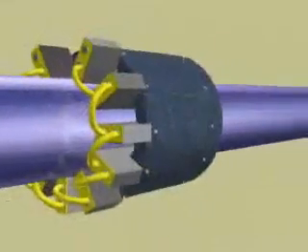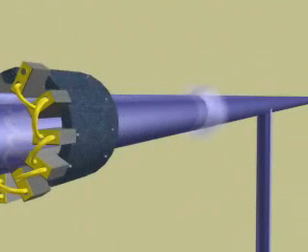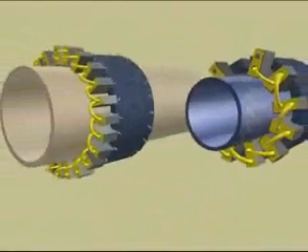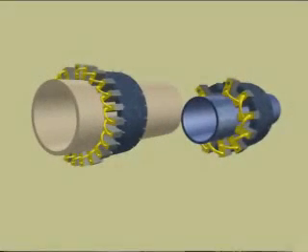The low-frequency sound can travel long distances along the pipe — several hundreds of meters under ideal conditions. So by transmitting the sound a long distance, we can examine large lengths of pipe in one go. Because it's a modular system, we can modify the transducer collar and test pipe upwards of two inches diameter, using the same system for all sizes.